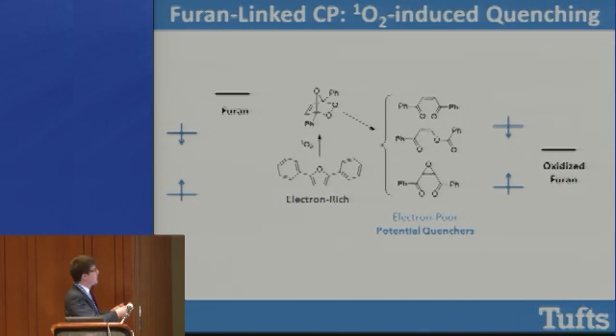Upon cycloaddition with singlet oxygen and subsequent reactions, this endoperoxide is not stable at room temperature, and we form these oxidized products that are now much more electron poor. And being electron poor, they can more readily accept electrons by being reduced. And so what we've done is take that furan orbital, that unoccupied orbital, and decrease its energy, such that, at least this was the hypothesis, we could then get an electron transfer event and see a diminution in fluorescence intensity upon exposure of this type of material to singlet oxygen. So that was the general hypothesis that we had going forward.